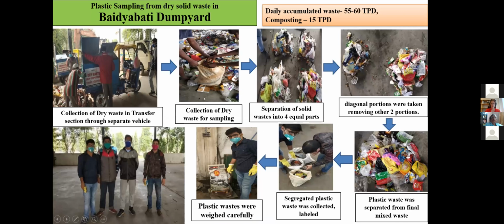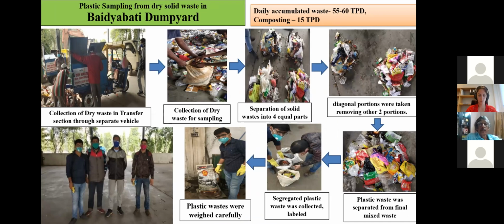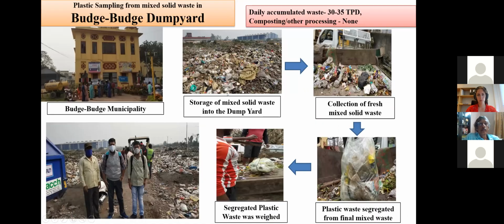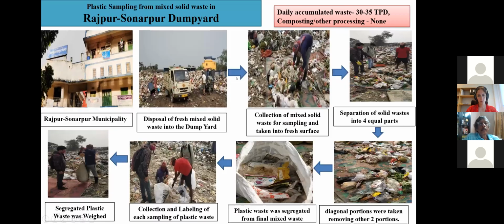Now shows the Baidyabati dump yard. The Baidyabati dump yard had a composting facility in which they were composting 15 tons per day, but the total accumulated waste was 55 to 60 tons per day there. Now let us come to Budge-Budge. In Budge-Budge, they had no composting or other processing, but the daily amount of solid waste was 30 to 35 tons per day. And this shows how we did the sampling.